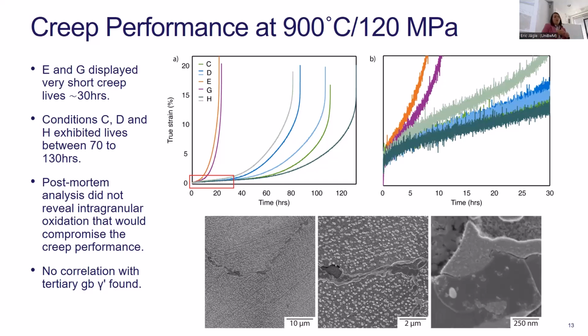So exploring a little bit more the literature, it seems that some of the key factors for the creep performance of Haynes 282 is actually down to the molybdenum content in the gamma phase. And because we've changed the carbide precipitation sequences, we're now locking quite a lot of molybdenum in the M6C carbides, right? So there's not as much of it in the matrix. And even 1 weight % change in the molybdenum content is causing a huge change in the creep properties. So we think that's the key reason that we're seeing that massive difference in the creep performance.